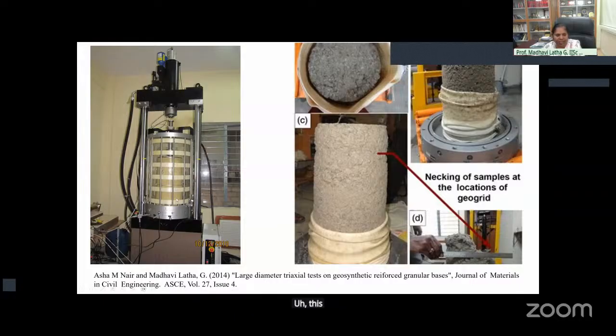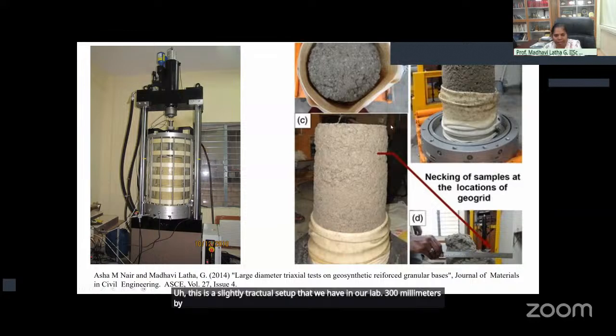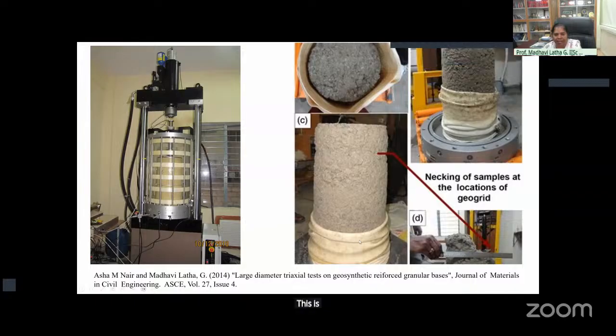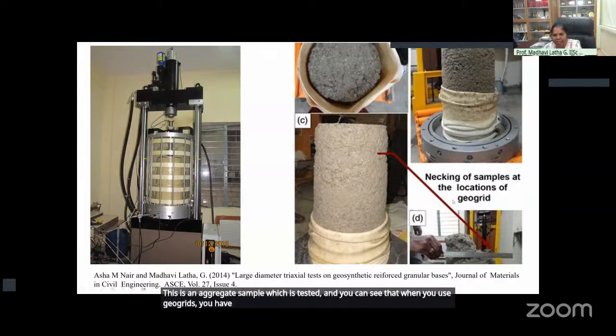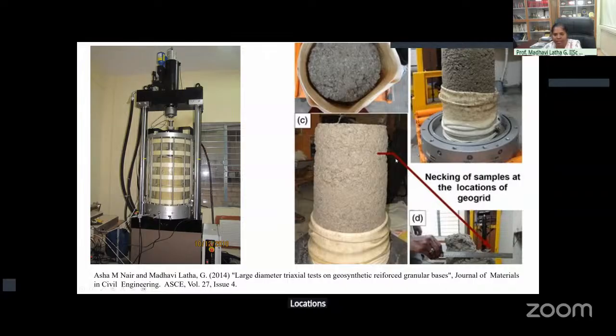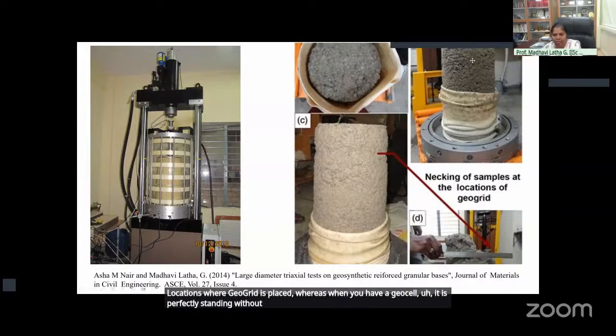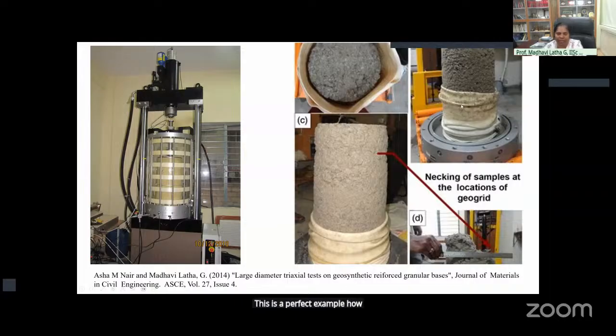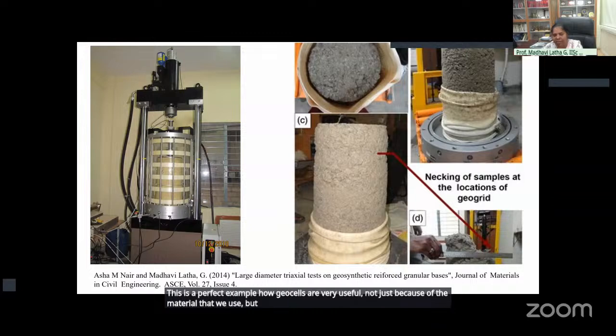This is a cyclic triaxial setup that we have in our lab. A 300 millimeter by 600 millimeter specimen can be tested. This is an aggregate sample which is tested, and you can see that when you use geogrids, you have necking of the samples at locations where the geogrid is placed, whereas when you have a geocell, it is perfectly standing without any disturbance throughout the length of the 600 mm, which is more than half a meter in size. So this is a perfect example of how geocells are very useful, not just because of the material that we use, but mainly because of the configuration of the interconnected cellular network.